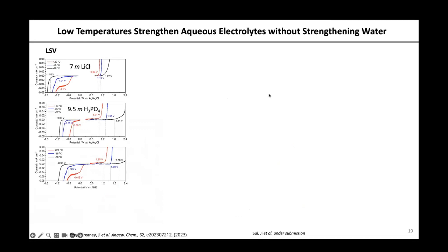Now, I want to actually highlight a new result that we just discovered by lowering the temperature of aqueous electrolyte. So this is a lithium chloride or a phosphoric acid electrolyte. They can stay as a liquid at very low temperatures. At minus 70 degrees Celsius, they stay as a liquid. Right? So this allows us to test their electrochemical stability window. So by lowering the temperature from 20 degrees to minus 78 degrees Celsius, we notice that the window for both electrolytes is dramatically increased.